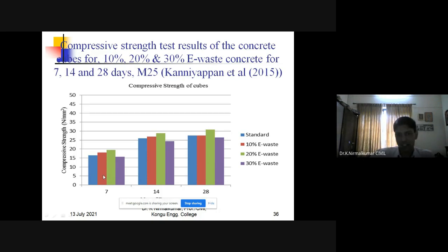At the seventh day test, 10% e-waste is a little bit more than the conventional concrete, and 20% has more compressive strength than the conventional one. At 30%, the concrete strength decreases and is a little bit less than that of the conventional concrete. So his inference for the seventh day compressive strength is that beyond 20% the compressive strength decreases. Almost the same thing is observed in the 14-day and 28-day strength.